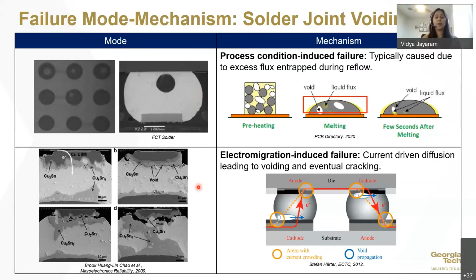But another type of void formation can be electromigration induced. This can happen over time while the product is in use, where it's a current driven diffusion, as you can see in the mechanism here, that's causing these voids. And electromigration can also cause the voids to grow and cause solder cracks or opens. So it's really important to understand when you see a failure, what is causing that.